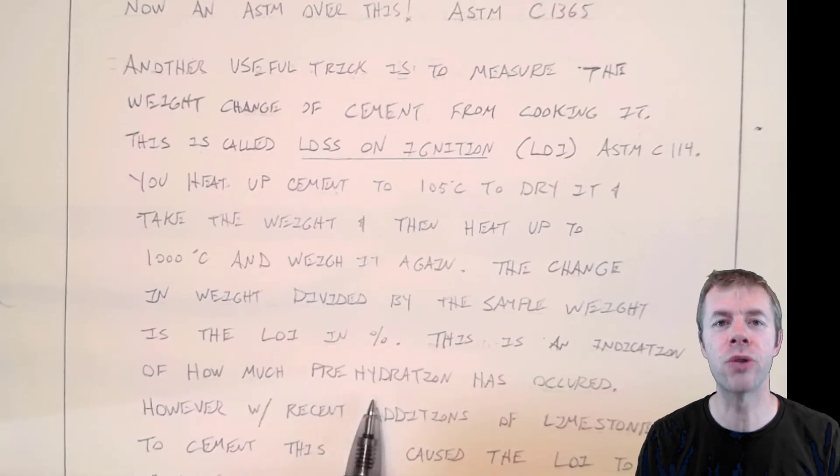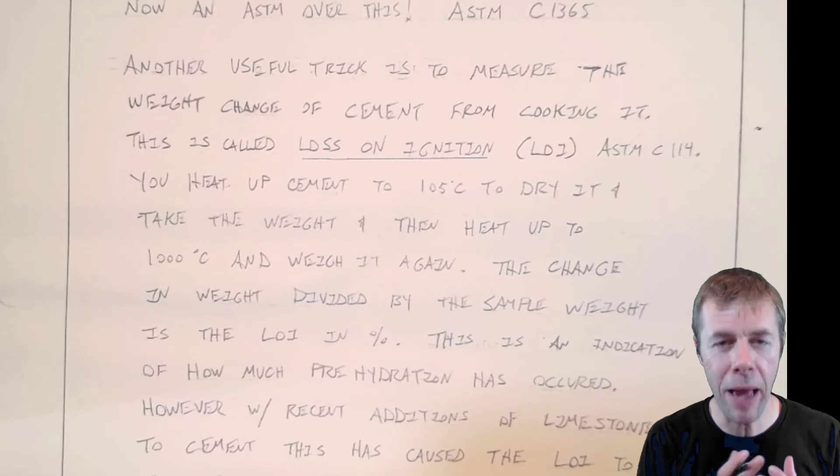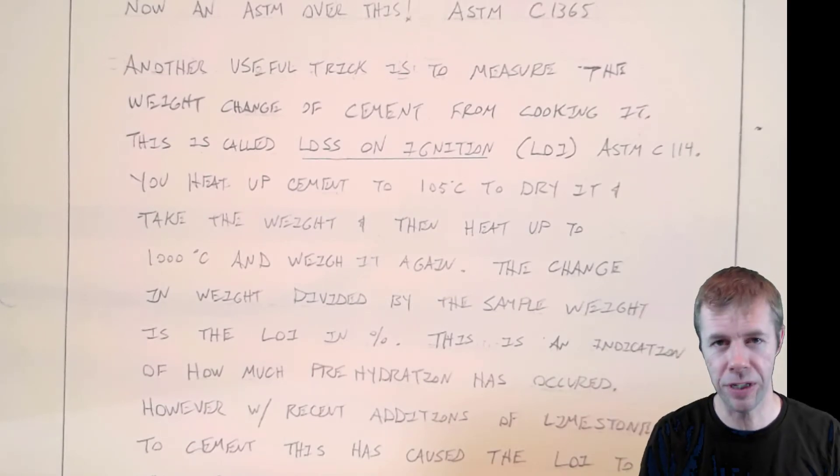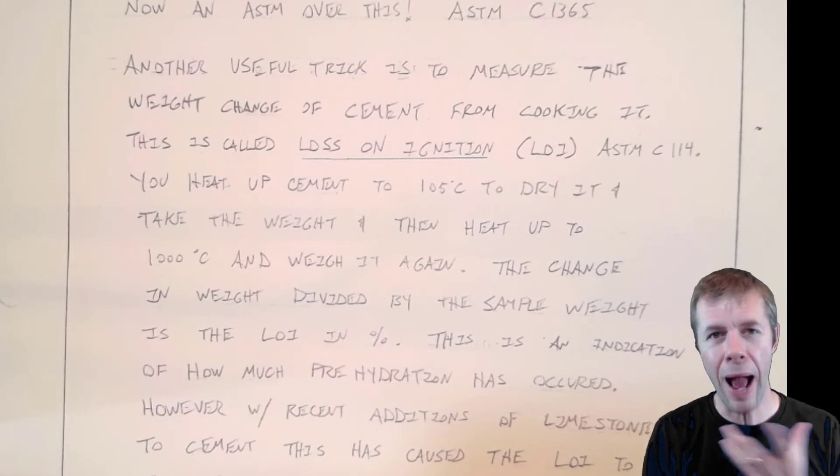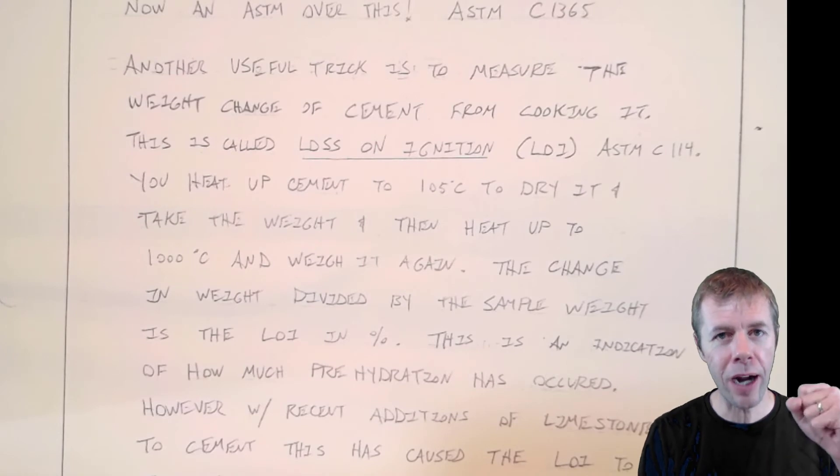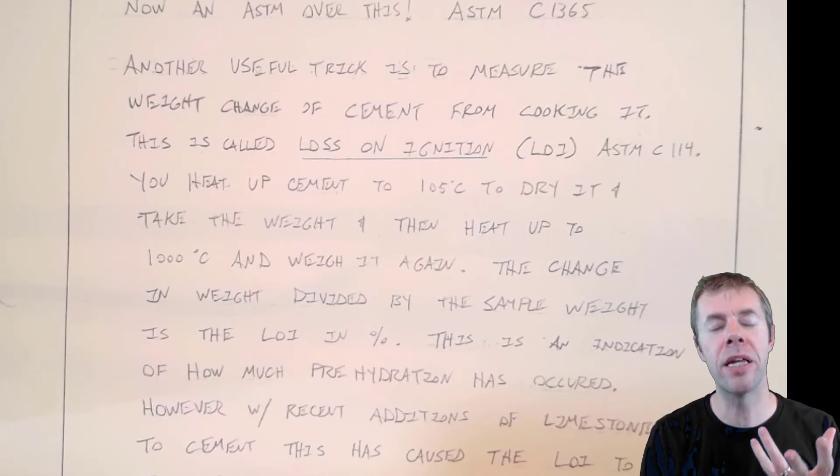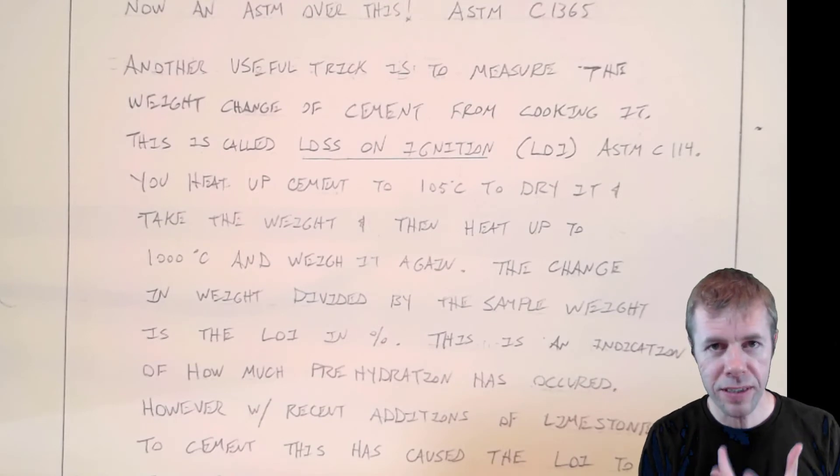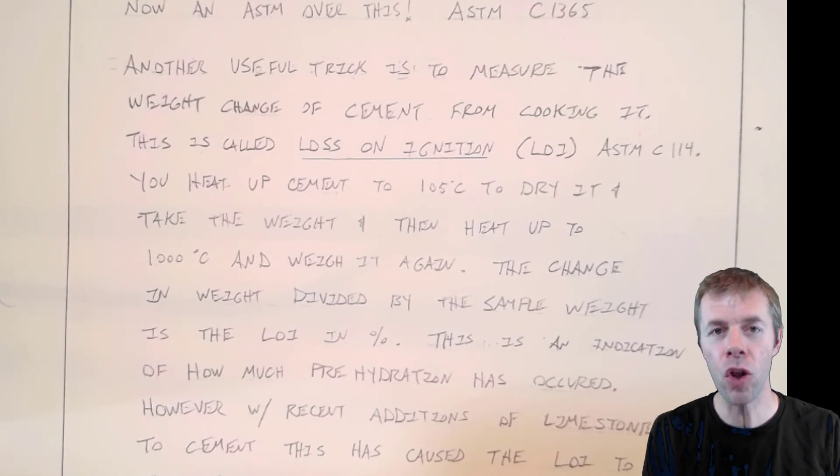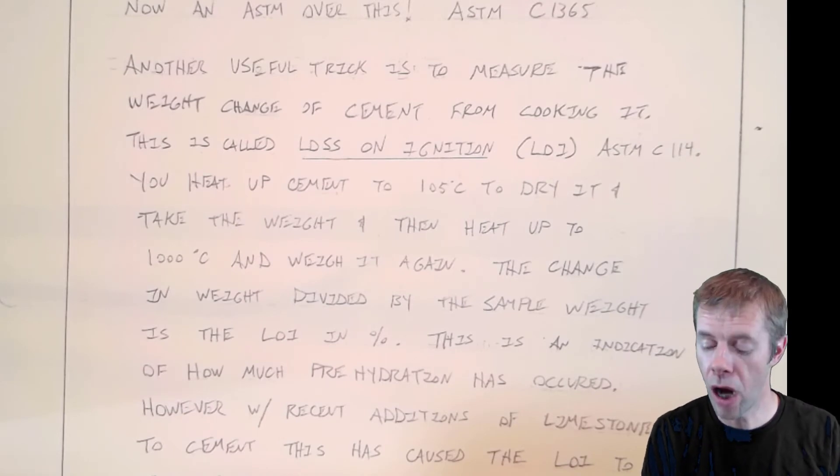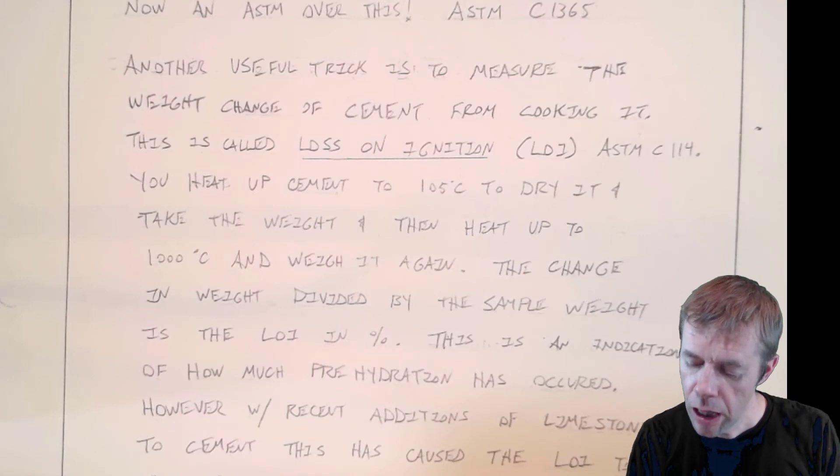It's an indication of how much pre-hydration has occurred. Remember, when we make cement, we've already gone way above 1,000 C. So anything that may be hydrated will actually combust and won't be there anymore. This test tells you how pre-hydrated the cement is. If you're in a very moist environment, or if you have an old bag of cement or old container and you're worried about it, an LOI test is a great way to evaluate if it's pre-hydrated or not.